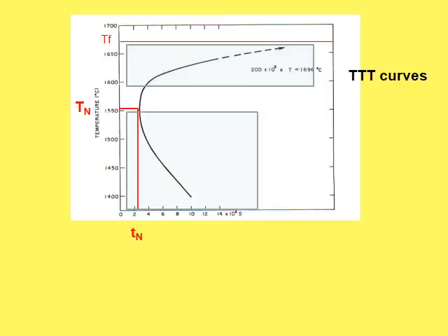However, for even lower temperatures, the situation changes surprisingly. The time to get crystals increases for lower temperatures. Here you must consider that, in parallel with the increasing thermodynamic tendency to crystallize as the temperature goes down, the viscosity dramatically increases. The increase in the viscosity hinders the crystallization due to the lower mobility of the species. These opposite effects, playing on the supercooled liquid, give this nose form to the plot.